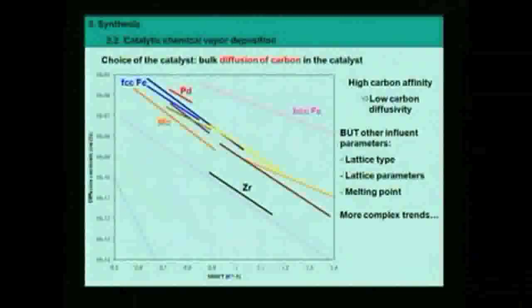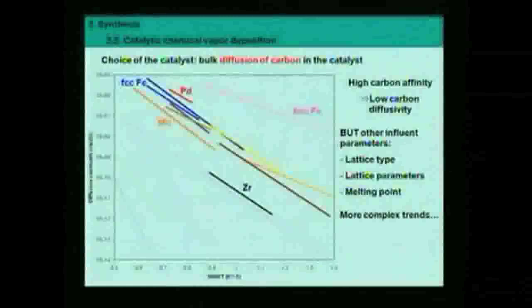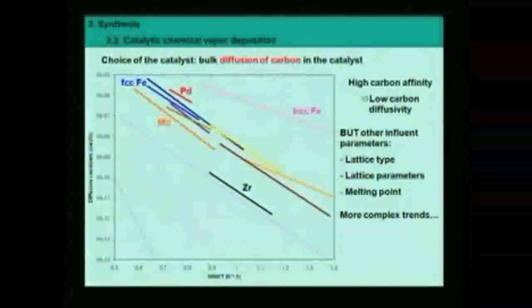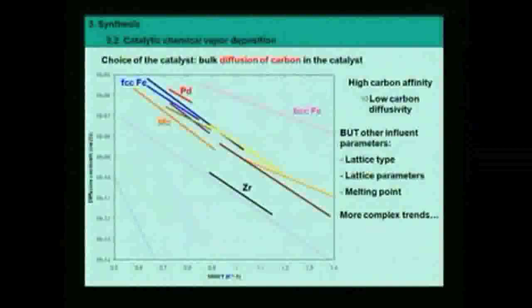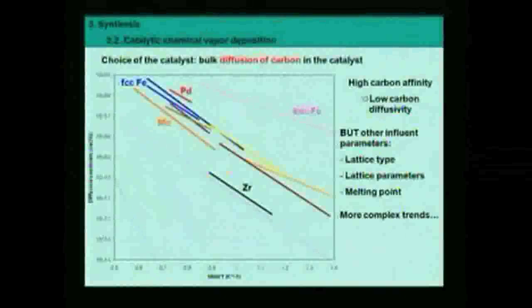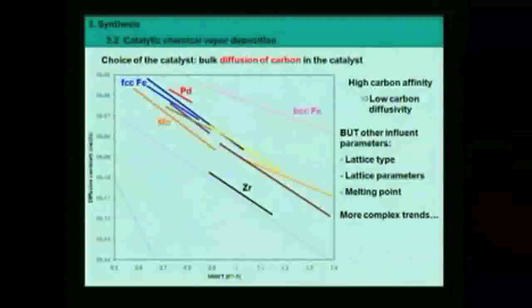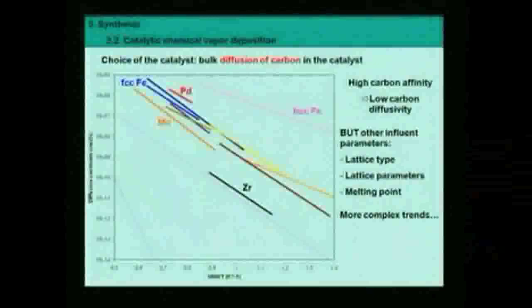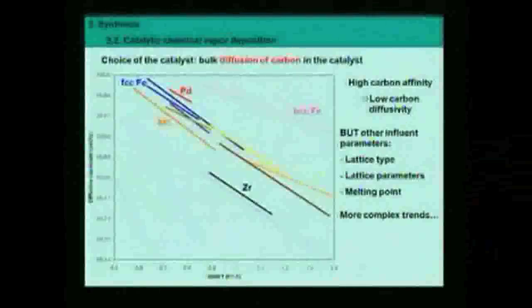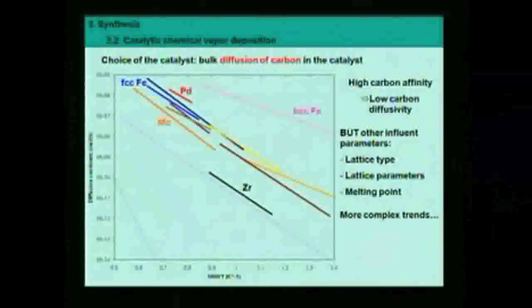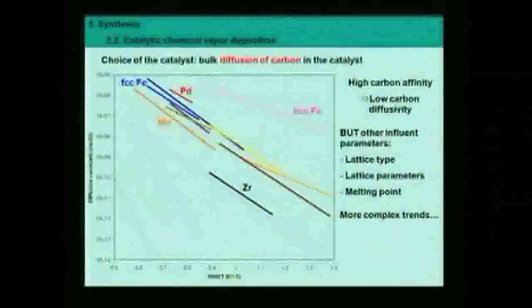It can be BCC, it can be FCC, for instance. And you observe, for iron, there is a change of crystal structure at about 600 degrees C. I may be wrong, but this is the order. And you see that in BCC iron, the diffusion is much faster than in FCC iron. So it's not as easy as previously to give trends just as a function of the carbon affinity. Diffusivity is dependent on carbon affinity, but not only.